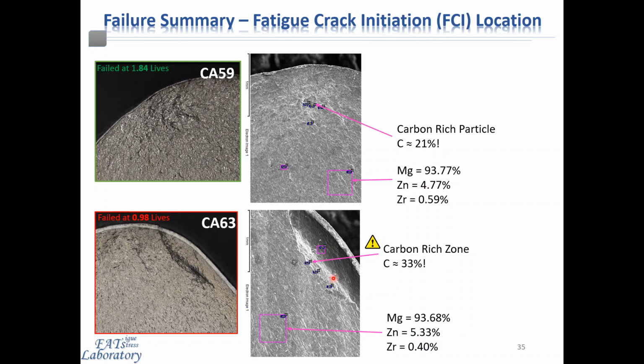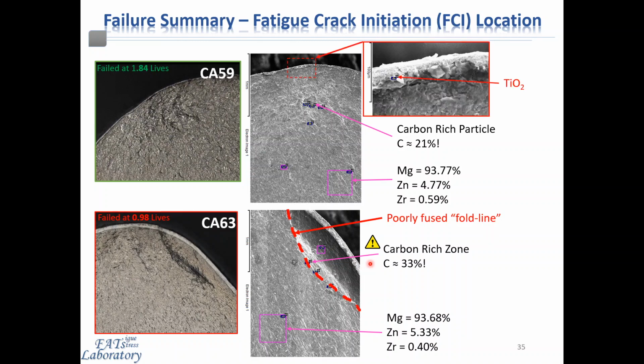Now carbon is not present in this particular magnesium alloy in detectable quantities. However, we're seeing greater than 30% carbon in some regions here. The source of this carbon is the graphite lubricant, which was used to lubricate the die surfaces during forging to facilitate better material flow and complete die filling. In general, this graphite stays at the surface most of the time. However, this particular region of the forging folded inward upon itself, and it entrained a high concentration of this graphite subsurface, which resulted in poor fusion.